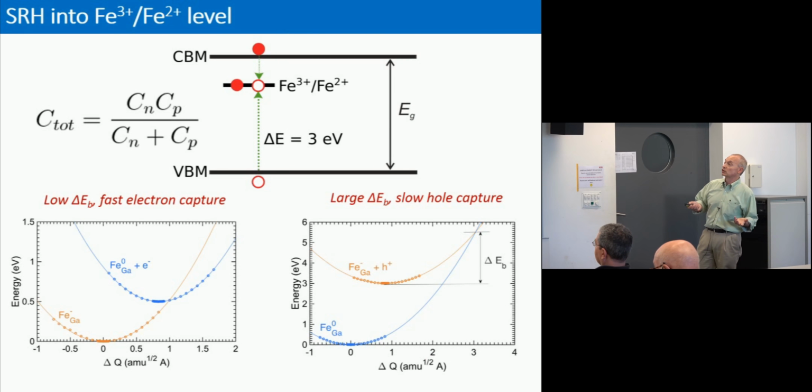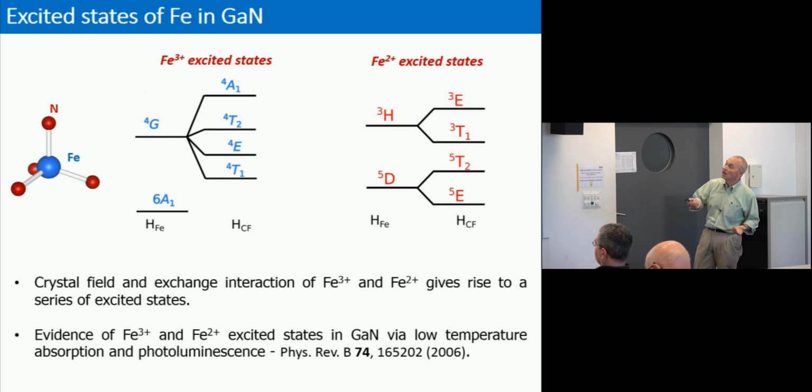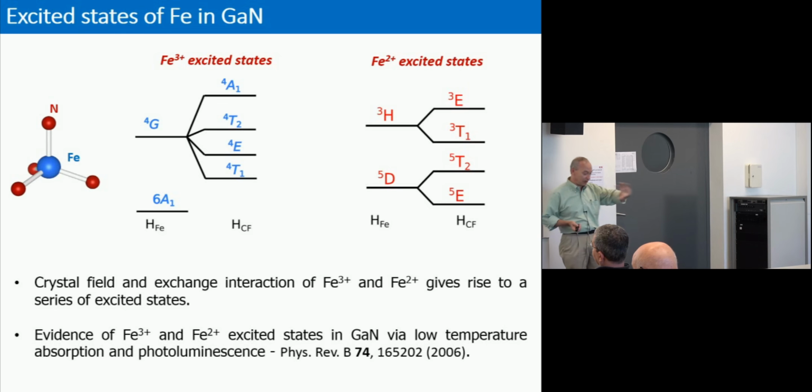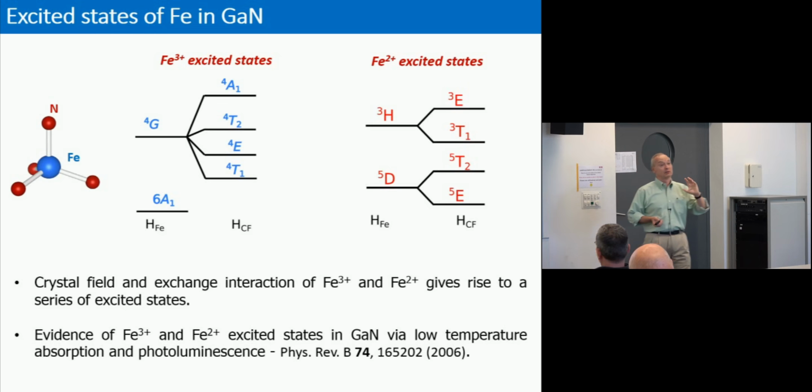Okay. So we went through the whole machinery of doing first principles calculations, but ultimately what mattered most was when we started taking into account that for each of these two possible oxidation states, either 3+ or 2+, there are a number of excited states possible. Now, that's actually reasonably easy to visualize in the case of a transition metal impurity such as iron. You have D states, right? And for these particular oxidation states, like for the 3+, you have 5 of the D states occupied with electrons.